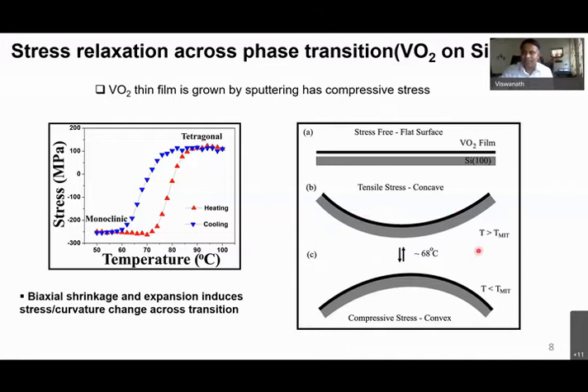The picture here, I think, is probably exaggerated. We will not find such a large curvature change. The idea is, VO2 during the phase transformation, what is happening? It is going from compressive stress to tensile stress, because there is a volume shrinkage happening across the phase transformation. That is what causes this tensile stress development during heating. So ultimately, after measuring the curvature and putting in the other parameters, we will be able to get the stress as a function of temperature.